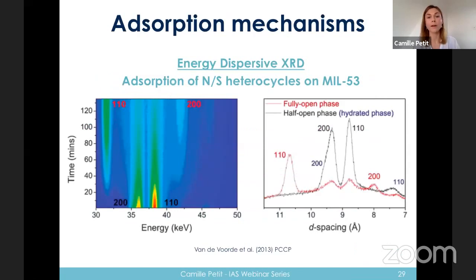So I take, for instance, here the example of energy dispersive XRD, so X-ray diffraction, where here you're using a polychromatic light, and this is done at a fixed angle. And what you will monitor is the change of the structure. So I take here the example of MIL-53 upon adsorption of different heterocycles that contain nitrogen and sulfur. And if you consider first the map on the left here, we have the energy here and the time here, and you see that the color map will change, and the numbers that you see here correspond to the Miller indices.